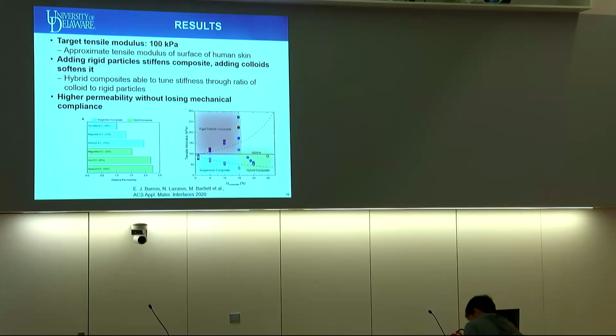And so we found that adding rigid particles stiffens the composite, as we'd expect. Adding colloidal materials softens it. The big advantage of this approach is that we can effectively tune the stiffness through the ratio of the colloidal to the rigid particulate. We're able to design in the resulting mechanical properties and gain higher permeability without losing mechanical compliance.